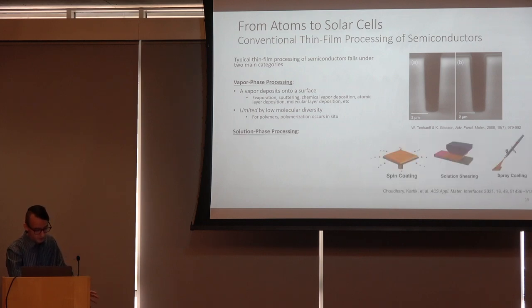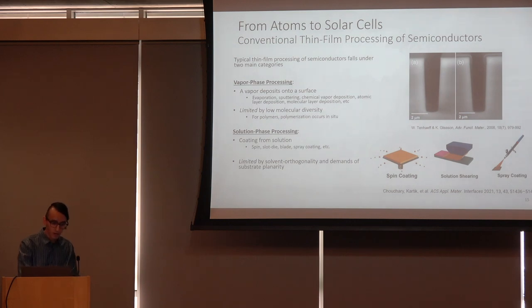And then on the other side, we have solution phase processing, so this would include things like spin coating, slot die coating, blade, spray coating, etc. And these techniques are limited by solvent orthogonality, which is this concept where if you're depositing something from solution, you need to make sure that whatever solvent you chose isn't dissolving the underlying layers. And this can place very significant restrictions on your processing. And then typically, in order to get a uniform coating, it also demands substrate planarity, which, as we will see, is kind of a problem for photovoltaics.